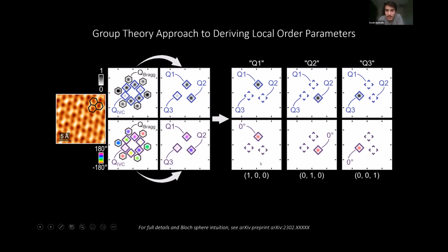This basis vector is multiplied by a new complex number, which we call the local order parameter, in order to match the FFT peak that you see in real images. We would then track this complex prefactor as our local order parameter. You can clearly see that this is a spanning basis set for projected FFTs like this. It will cover anything that we see in experiment, as long as it's described by this FFT.